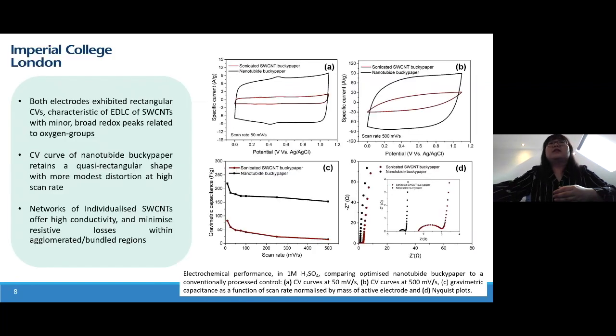So as you can see from the cyclic voltammetry curves, in both lower scan rates and higher scan rates, both of them show the rectangular shapes of EDLC behavior, which comes from the single-walled carbon nanotube nature itself, and the minor small redox peak comes from the oxygen functional groups.